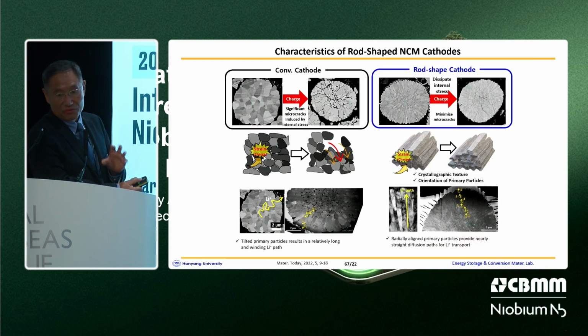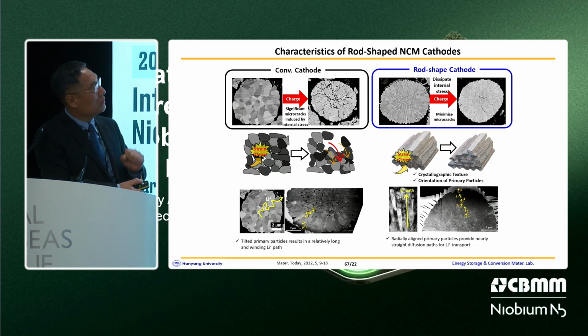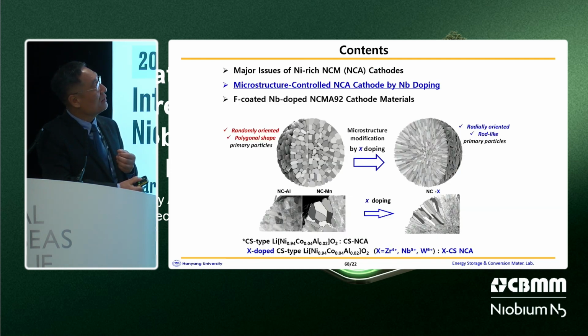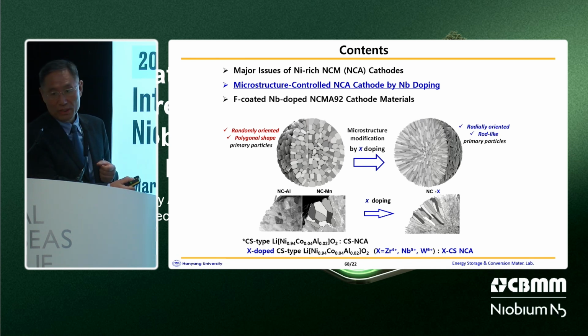And these are the characteristics of rod-shaped cathode materials. As you know very well, a conventional cathode is composed of large polygonal-shaped primary particles. This material can easily develop significant microcracks, induced by the internal stress during the charging process. In comparison, rod-shaped primary particles can easily dissipate internal stress and thus minimize microcracking. And let me introduce the microstructure-controlled NCA cathode by niobium doping.